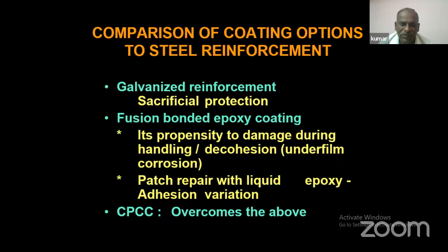That is one thing. Second thing, the patch repair work. In patch repair works, people are using epoxy. And also, while pouring the concrete, it creates small pinholes. Through the pinholes, water or contaminants go inside and create underfilm corrosion. The outside of the coated reinforcement looks good, but on the surface of the steel reinforcement, you will be getting corrosion. That is called underfilm corrosion, which has been reported by Andrade as well as Professor Sagüés from the US. They have published so many papers on it. Then that also does not serve the purpose.